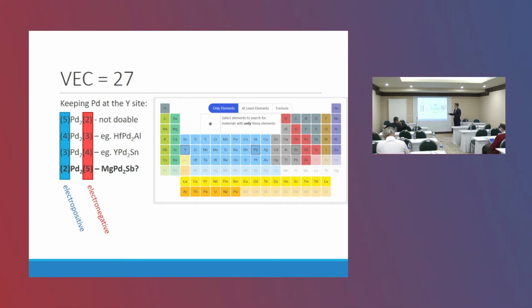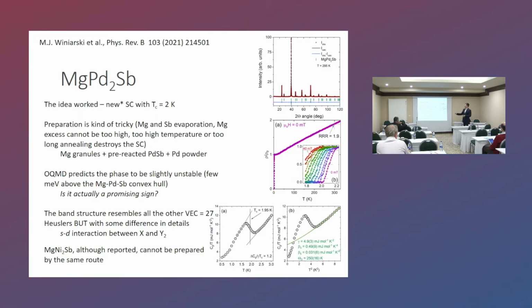So a pentavalent electropositive cation like niobium wouldn't work because there are no bivalent electronegative ones. 4-3 and 3-4 combinations are already all reported. So how about taking magnesium, a divalent cation, and then something pentavalent like antimony? And it turns out it worked great. We found a new, with an asterisk, superconductor, new because we had a reviewer who said that it was reported some years ago, which was like one line, not even a line, one figure in a 2-page paper giving the unit cell parameter. But let's say it's new-ish.